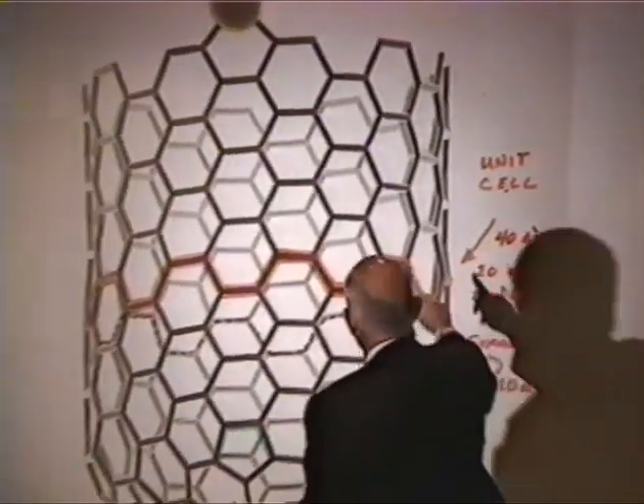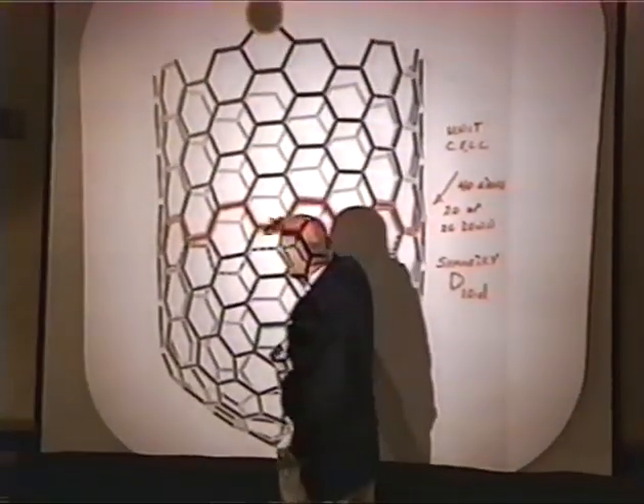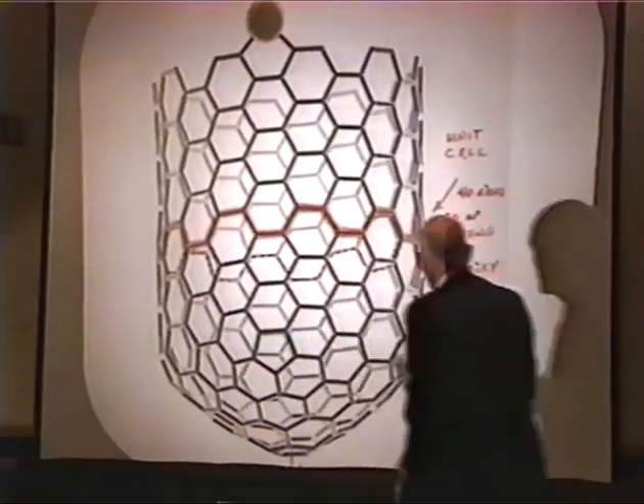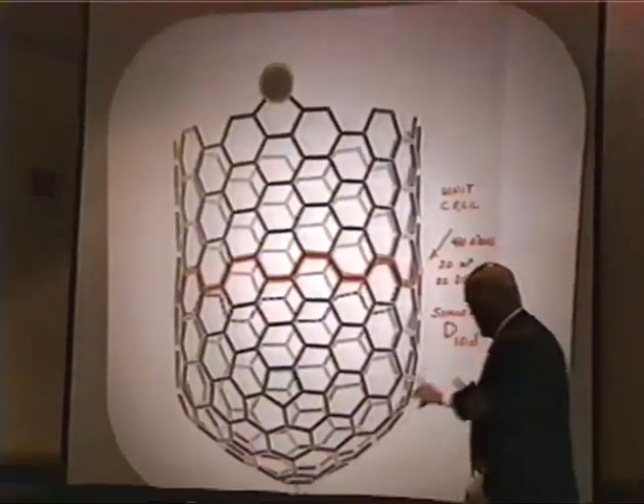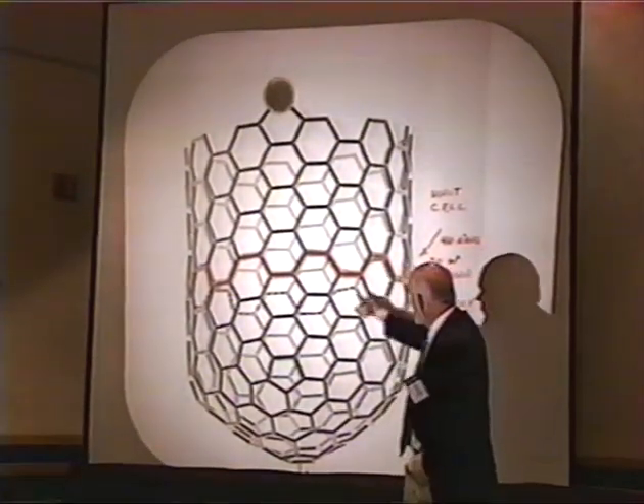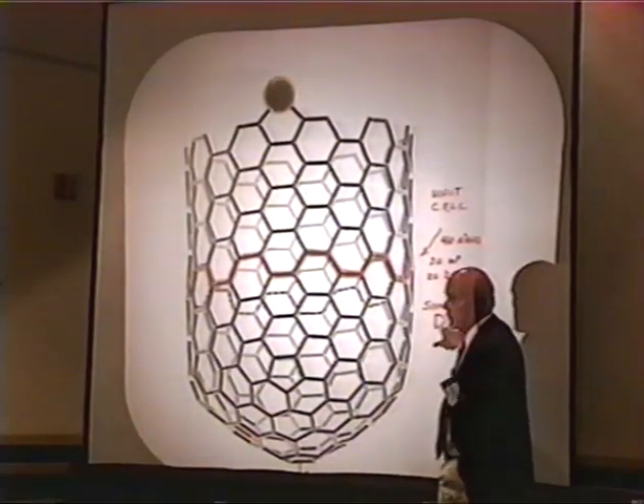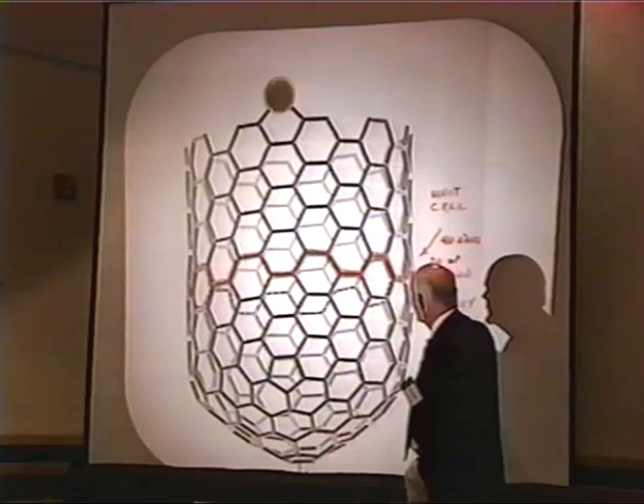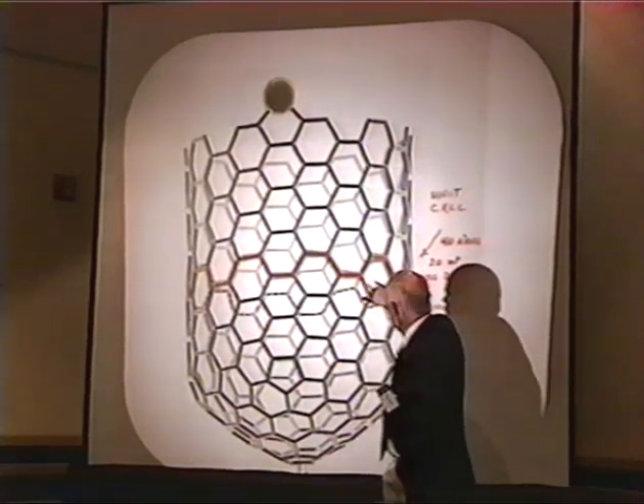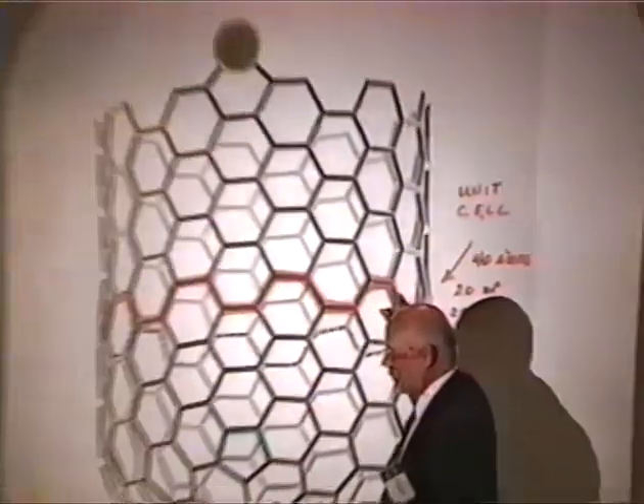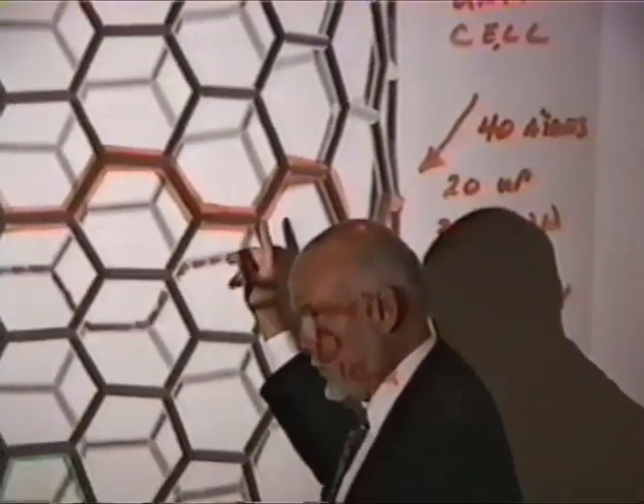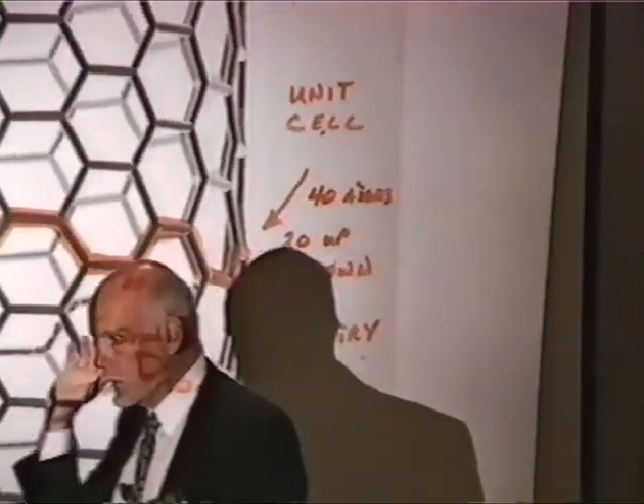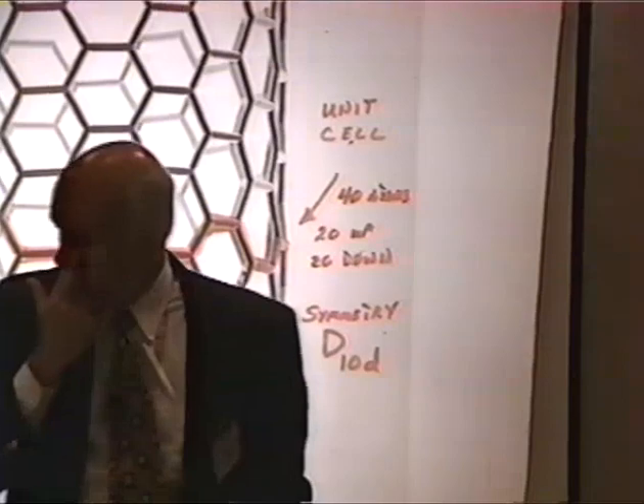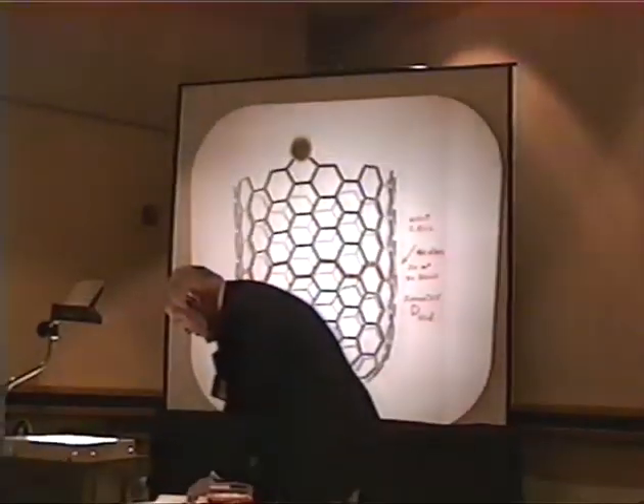The unit cell of this tube is this thing that has 2 up and 2 down, going along that direction. In this tube, the point group symmetry of that unit cell, D10D, is sufficient that every atom is identical to every other one by symmetry. It shares with C60 this property. The symmetry is sufficient to completely determine the problem. It's quite a wonderful circumstance.